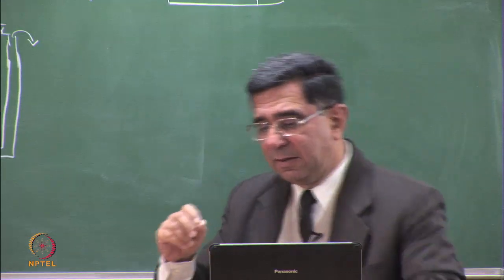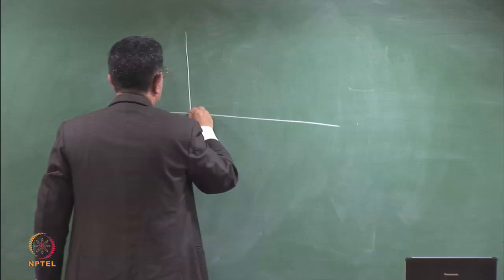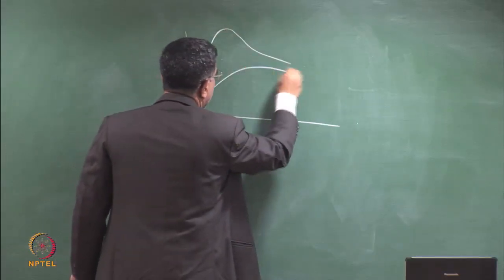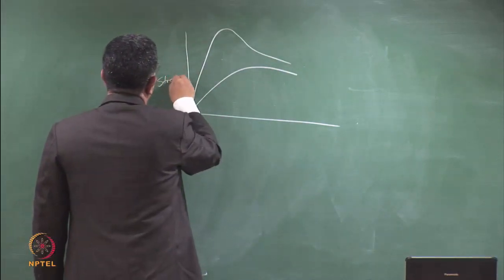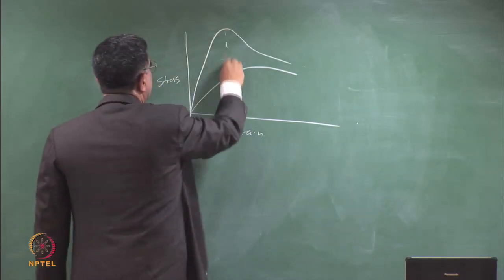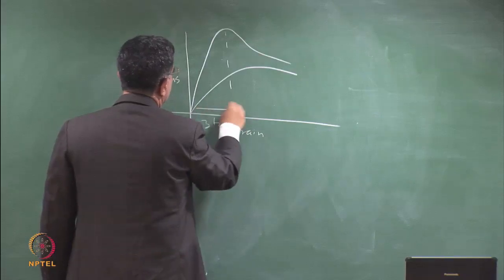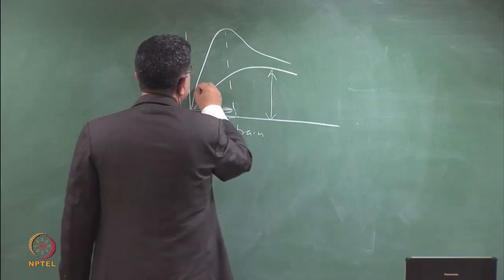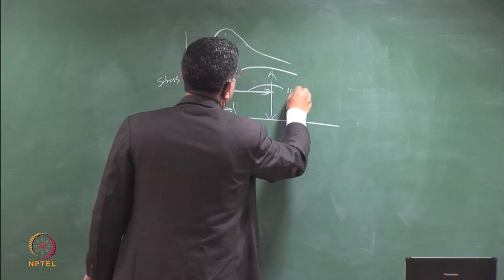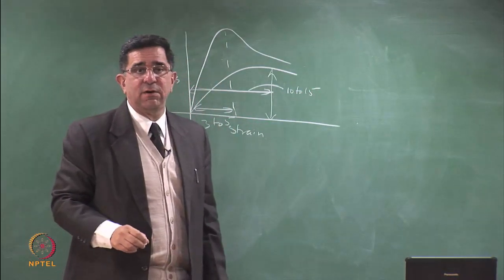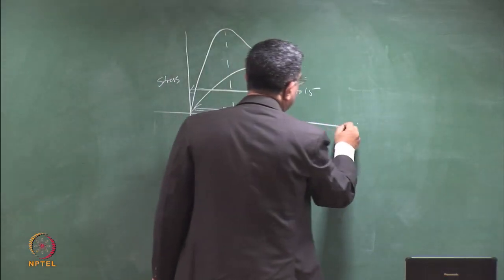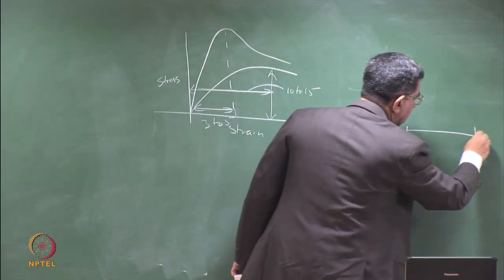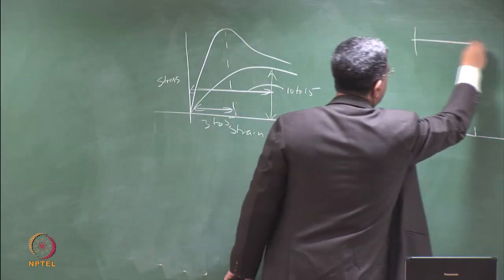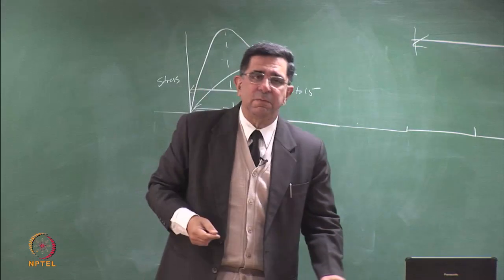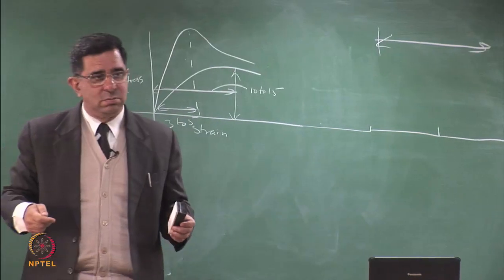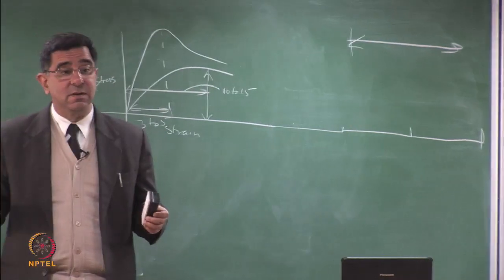You remember, in dense sand, the stress strain curve will look like this. You can have this behavior, or you can have this behavior. So this is stress, this is strain. And we said that in soils, in dense sand or stiff clays, this may be 3 to 5, and this may be 10 to 15. So where is the failure strain for an HDPE geomembrane? If this is 15, this is 30, this is 45, this is 60, and this is 75. So the range that we are talking of, HDPE will have failure in that range. It can be also 100%. 50 to 100% is the elongation before a geomembrane fails. So it's a flexible material.